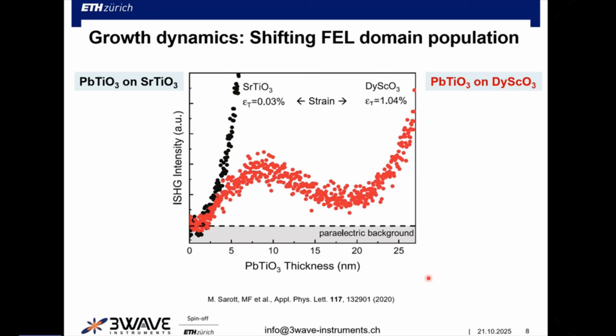Here is another example that is a bit more than conceptual and shows you the power of all this. What is the power of really watching something while it emerges and not afterwards? So here we have lead titanate, which is also ferroelectric, while it grows on 2 different substrates. Strontium titanate without strain, and then you see while you grow your film, this frequency doubled signal increases. So apparently your film gets thicker, so more polarized material, more signal.